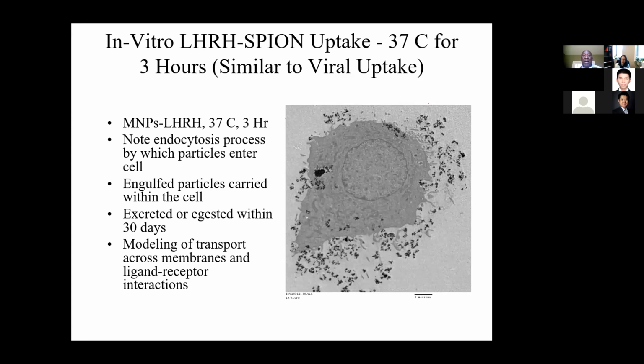Now, in thinking about how the nanoparticles go into the cells, we've done some in vitro experiments and in vivo experiments to understand the processes. And what we find is that when the nanoparticles interact with the cells, you have clusters that form due to particle coagulation and adhesion, the disturbance of the cell membrane that enables you to have elastic bending of the membrane, and then the encapsulation of these particles and their transport into the cytoplasm, and in some cases, possibly into the nucleus.